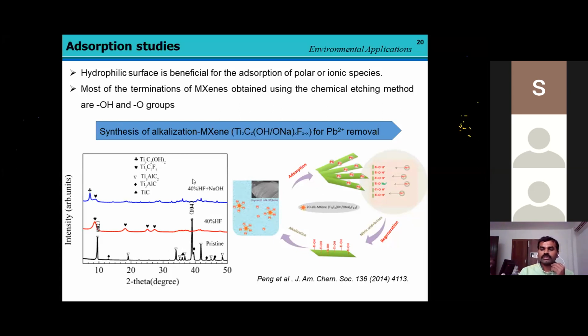with the help of hydrogen fluoride, this material was used to adsorb lead ion with an initial concentration of 50 ppm. Then it showed that the adsorption was by a cation exchange mechanism as well as complexation. Then the material was regenerated using a suitable eluent like nitric acid. Then you will get the original form of MXene. Then we can again incorporate sodium, and you will get the sodium form. Then we can utilize it further.